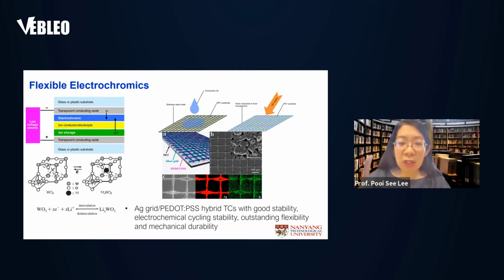Here, the challenge is to prepare flexible transparent conductors that can work on large area printable substrates. One of our approaches is preparing the silver grid that is conductive and transparent because of the large opening array and very thin silver lines that are connected to each other, providing the electronic transport. While in order to improve the electrochemical stability and oxidative resistance, a layer of PEDOT:PSS is also coated on the surface. That makes a hybrid transparent conductor that is very mechanically durable and has outstanding flexibility.